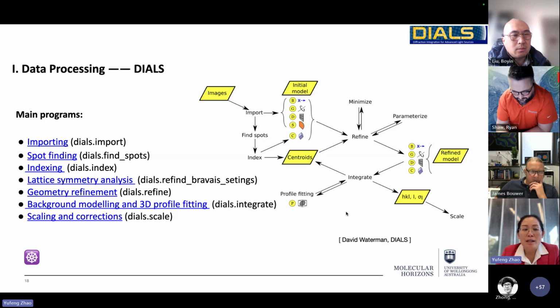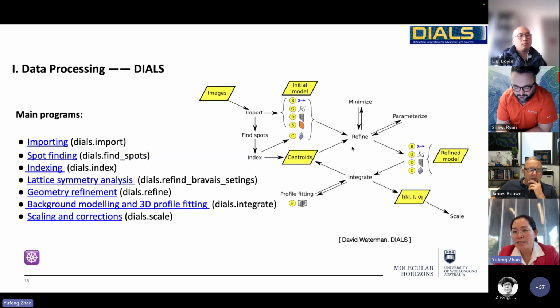All similar. And if we have similar quality of data through every software, you can get a similar quality of result. So the unique thing about DIALS is really about, for example, the find spots, indexing, refinement. It looks through the whole data set in one go. So XDS might process window by window. So the great thing is when we get to integration, nearly the final step, we already have a good model. And this is because integration is really computationally expensive.